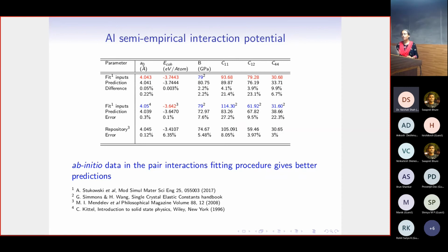Once we generate this semi-empirical potential, we use it in a classical molecular simulation software. In this case, we have used LAMMPS, and then we see how this potential is going to predict the different structural properties for that material. The prediction simply means that after we generated the interaction potential, we now use it to obtain the structural properties. So this is the predicted property, and then we look at how much difference we are getting in the prediction.